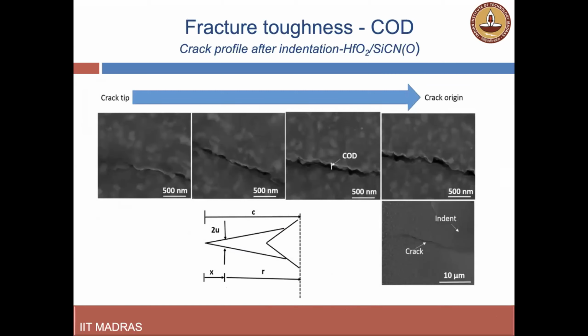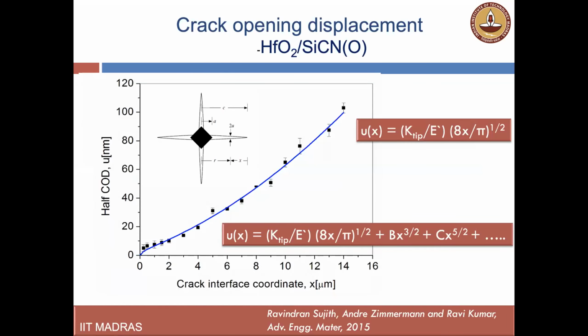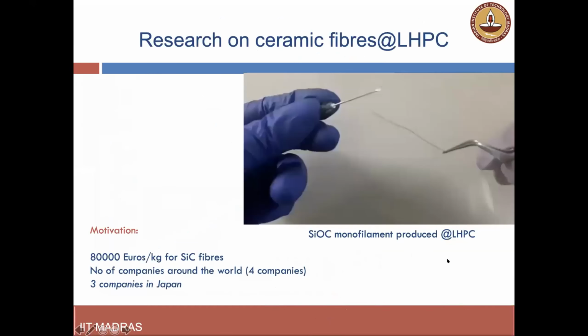You have to measure the crack opening from the origin of the crack till a certain point, so that you have sufficient data points to get the critical stress intensity factor, or fracture toughness, as we call it. And typically it's in the order of around 1 MPa root meter, not very high. So that is where we are still working at improving their fracture properties.